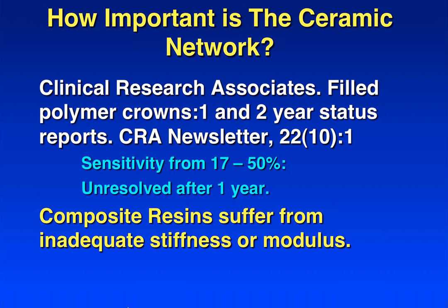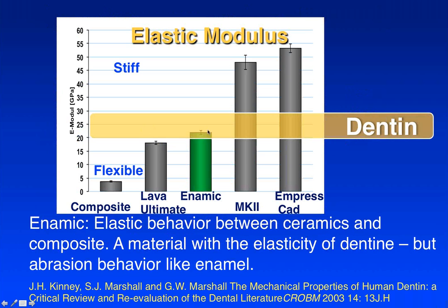The other problem is it has a very large thermal expansion coefficient. So as you're eating ice cream and drinking coffee, you get a similar effect where the crown is expanding and contracting with the different temperatures. One interesting property of Enamic is that the elastic modulus actually falls within the value of dentin. So when you bond a material like Enamic, which has a very similar stiffness value or modulus value to dentin, you get an overall structure which is very resistant to stresses that are being placed in the mouth.